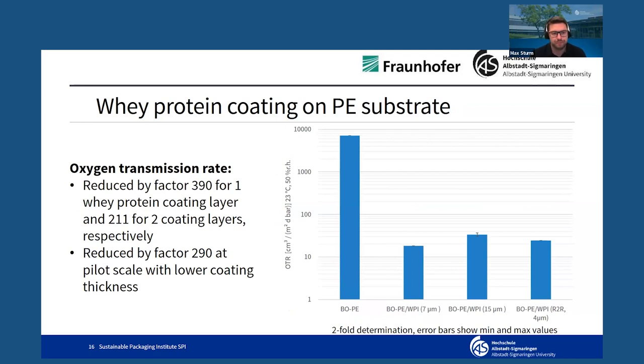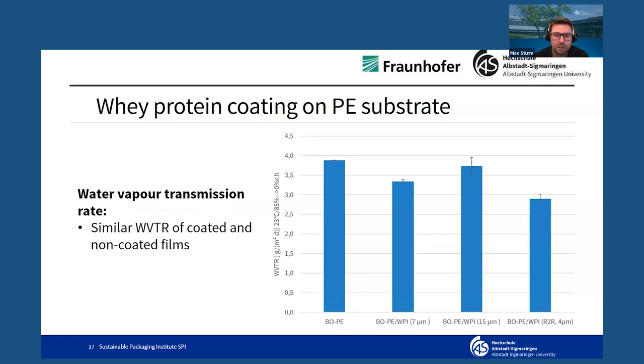Finally, we also applied the whey protein coating on PE films to cover most of the packaging films that are being used. Here we start with the PE film at approximately 7,000 cubic centimeters per square meter day bar. And this was reduced to about 20 to 30 cubic centimeters per square meter day bar for the coatings at lab scale and pilot scale. As you can see, these are quite similar results to what we saw for the other substrates. And similar to the PET films, for PE the water vapor barrier wasn't meaningfully impacted by the whey protein coating as well.